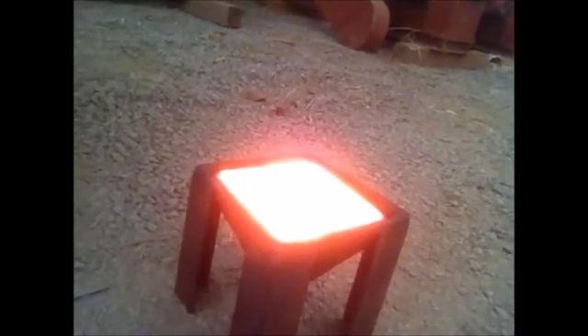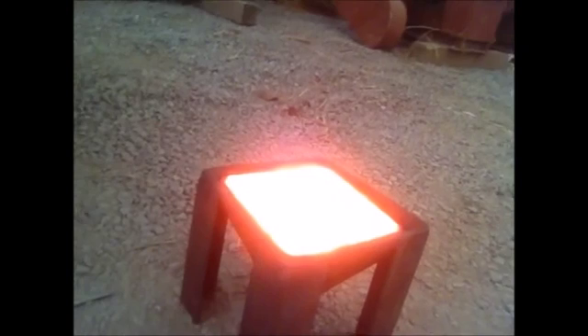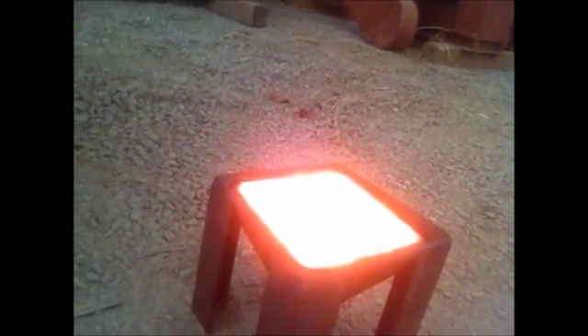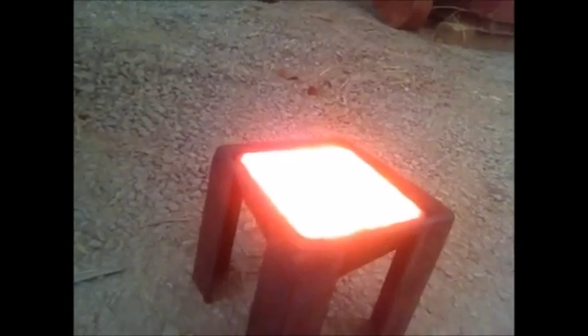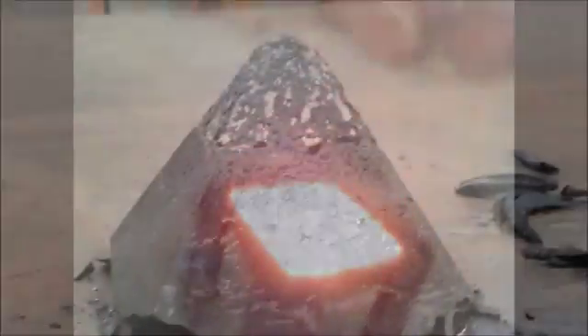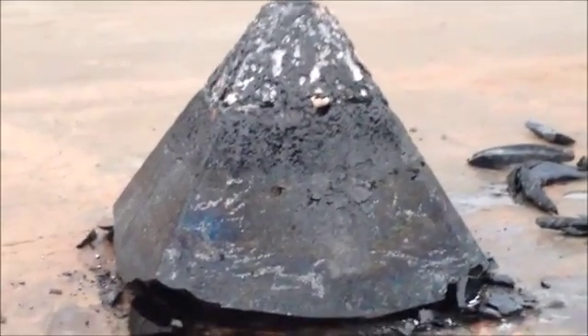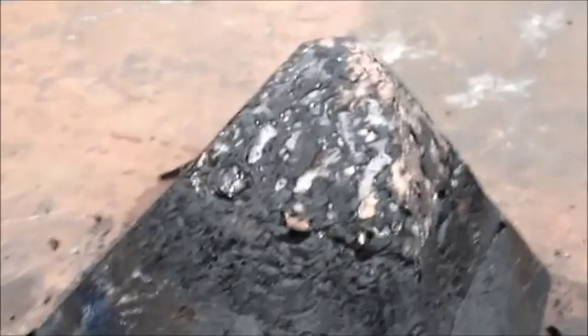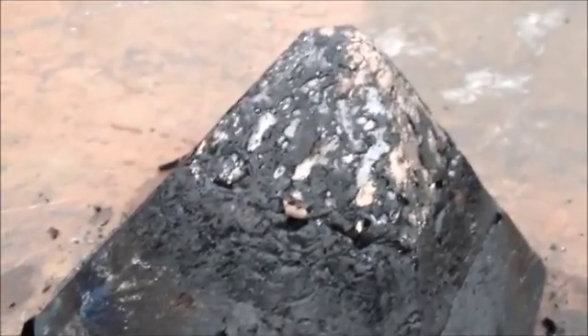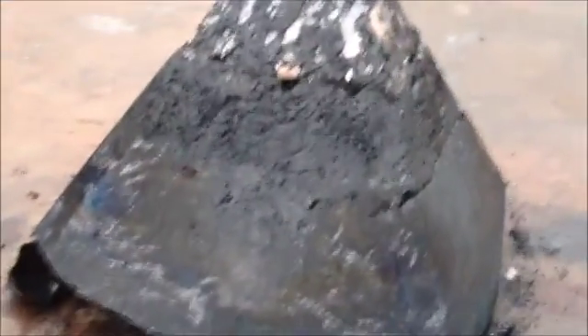Here's our conical mold with the pour in it. So we'll let that cool, and we'll dump it out and see what the collector metal looks like. So there you go, a couple taps on the table, and the slag and stuff fell out of the mold, and you can see the copper and metal all came down to the bottom, and then the slag is sitting on top. So I've broken our 3 different phases apart here.